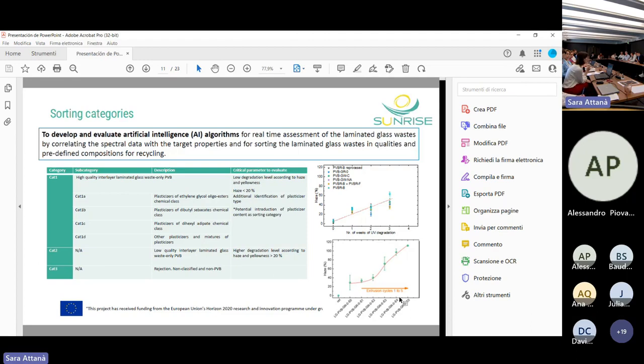So then we are working outside of the initially planned aspects to introduce an additional potential sorting category, which is the content of the plasticizer. With Raman, we can make some training of the sensors with the PVB and different content of plasticizer, and we could try to identify plasticizer compositions below some value and higher than some value. And this could also be interesting for classification.